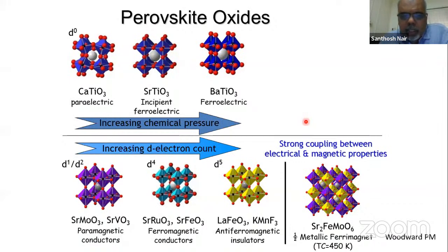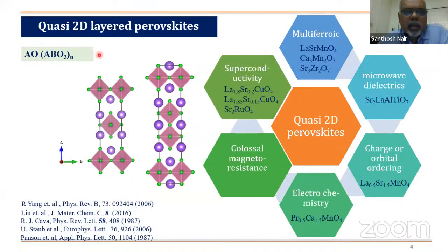So what we have done is make the system layered. For example, this is a perovskite building block, and then you start putting in another AO layer, which is a strontium oxide layer or a lanthanum oxide layer. These are the perovskite building blocks. You introduce something like this, so that it goes in between these perovskite blocks, or you can see better in this. These are the perovskite blocks, and then you incorporate the AO. You can see that there is a gap which forms.